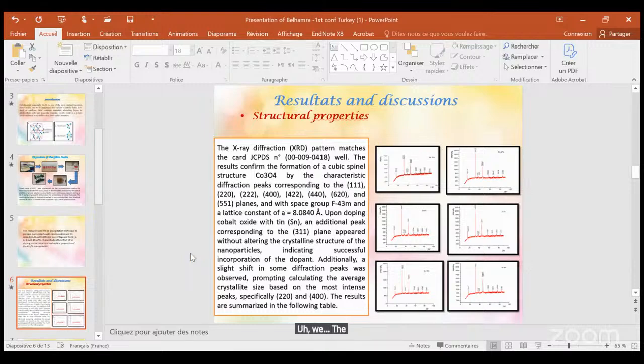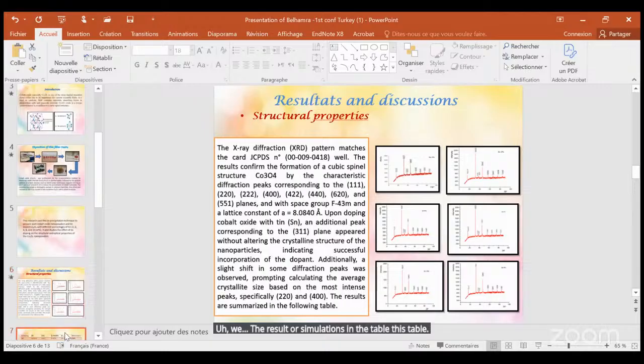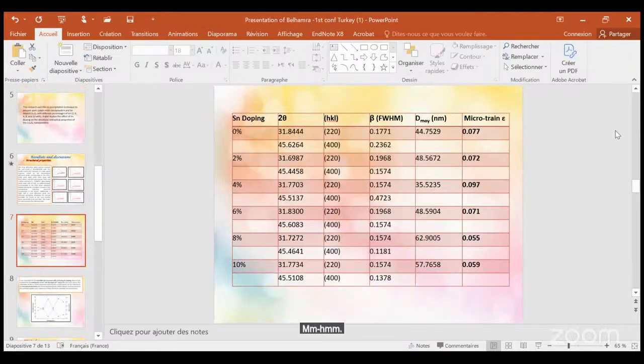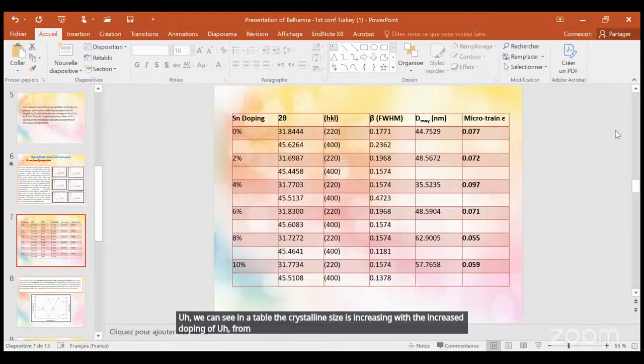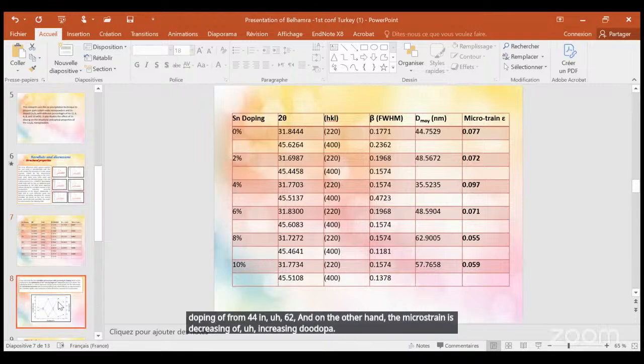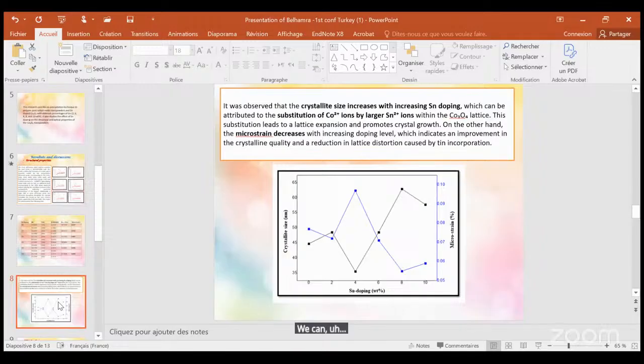The results are summarized in this table. We can see in the table that the crystal size increases with increasing Sn doping, from 44 to 62, while on the other hand the microstrain decreases with increasing doping. This can be attributed to the substitution of Co2+ ions by larger Sn2+ ions within the Co3O4 lattice.